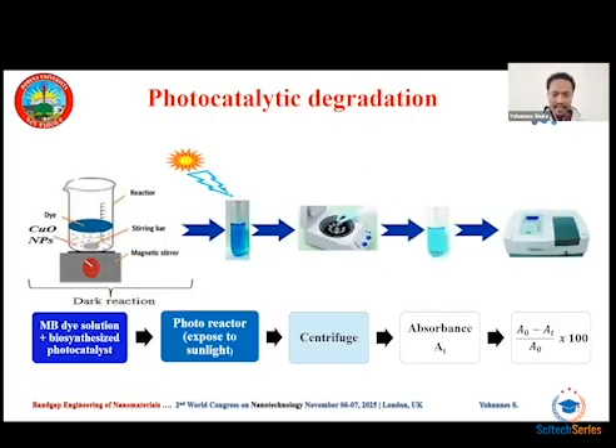After that, the material was taken for experimental characterization by using UV, XRD, FTIR, and SEM for morphology. Then the application was conducted by applying these types of experimental procedures. The first one is we take 1 gram of photocatalyst, that is copper oxide or the modified nanocatalyst. Then that nanocatalyst is reacted with 50 ml of artificial pollutant, which is methylene blue, and reacted in a dark room, that is called the dark reaction.